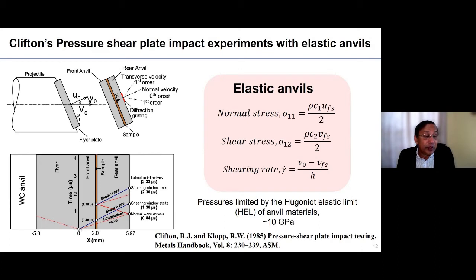So you generate both normal and shear waves in the anvil plates, in the target and the flyer plate. The longitudinal waves, or the pressure waves, propagate faster, and the shear wave trails. When the normal longitudinal wave arrives at the interface at the sample, there is a thin sample sandwich, and it reverberates within this sample. So it attains a sort of pressure equilibrium. By the time the shear wave arrives, this is normally at a constant pressure. Also, the advantage of such a sandwich technique is that you are creating a ramp loading. That means you are creating quasi-isentropic loading, so your temperature increase can be moderated.